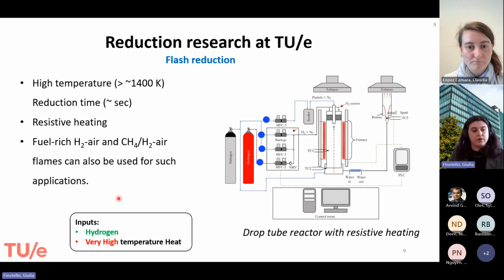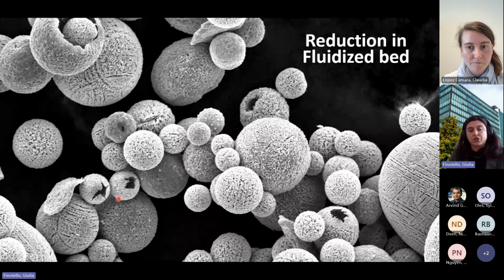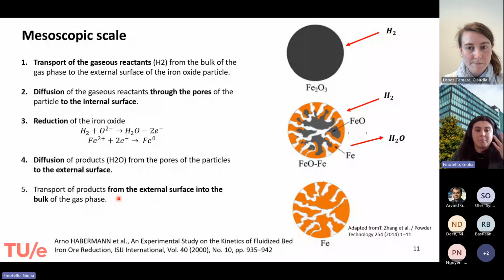So let's have a look at the reduction in a fluidized bed. In this case, you need hydrogen, we said, and you also need heat to provide a temperature of 500 to 900 degrees. At the mesoscopic scale, the mechanism of transport follows different steps. First you have the transport of the gaseous reactant from the bulk of your gas phase to the surface of your iron oxide particle. Then you have the diffusion of the gaseous reactant through the pores of your internal surface.